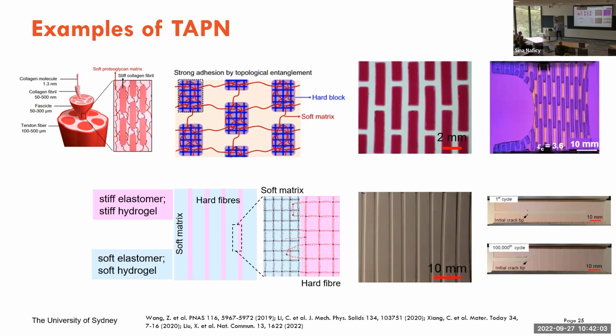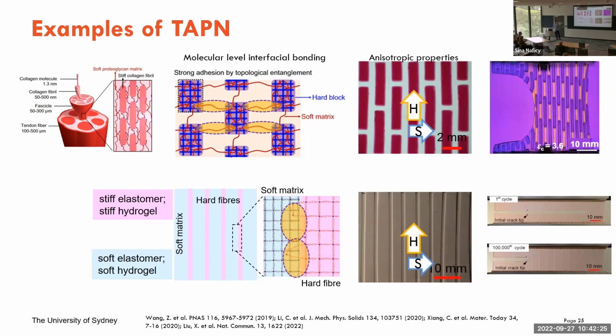And then we have a very broad interface. So at the top, in fact, the soft matrix is completely diffused inside the rigid parts. They're completely inside each other. And it's the same with the bottom part too. So they are cured together, these two. So what happens is that not only do we have the anisotropic properties, but because of the way they have been designed, the stress is now distributed over the whole length of the material.